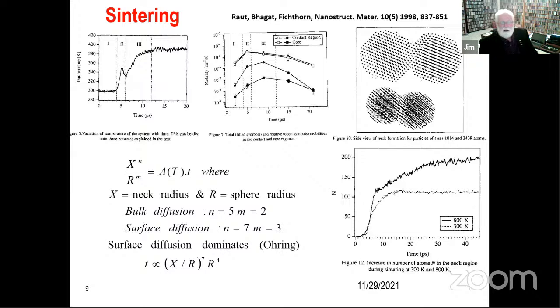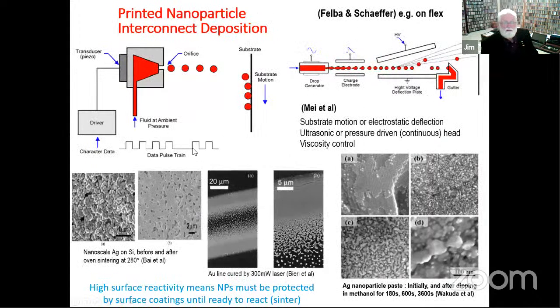So if you increase the particle size, then the time for sintering becomes larger and larger very rapidly. And the converse is true. Now sintering is used in creating interconnect patterns on a substrate. The substrate can move, and the jet of nanoparticles, like from a desktop printer, can be gone straight out, or they can be charged and deflected by plates to produce a pattern on the substrate.